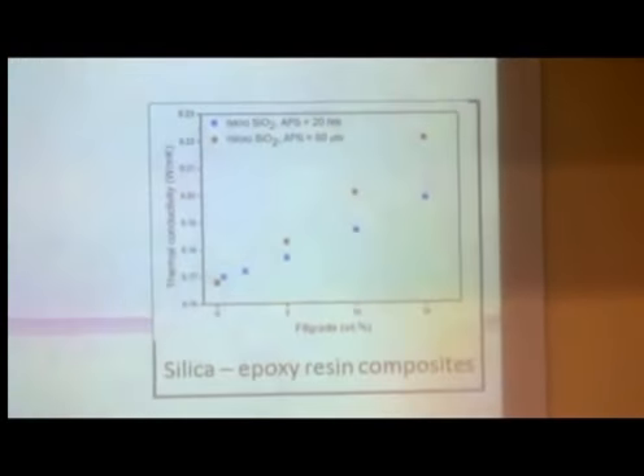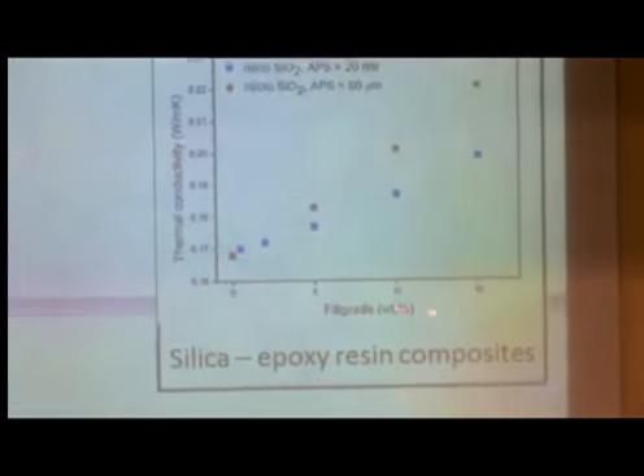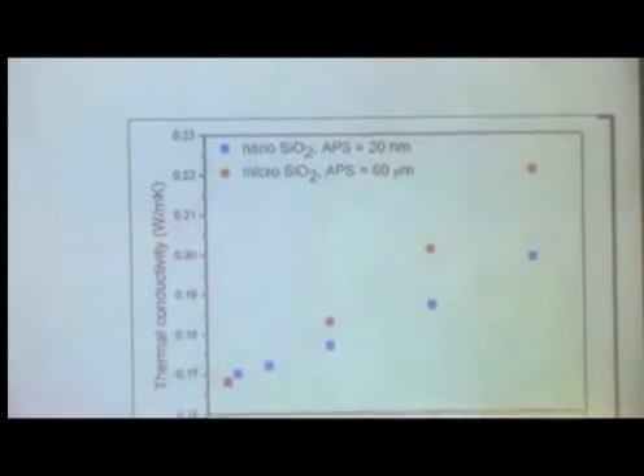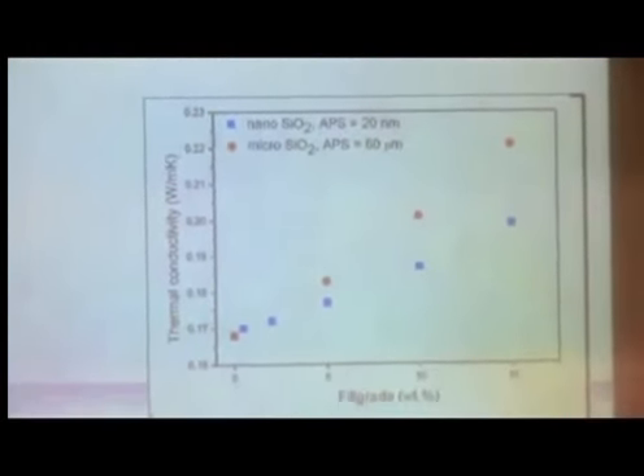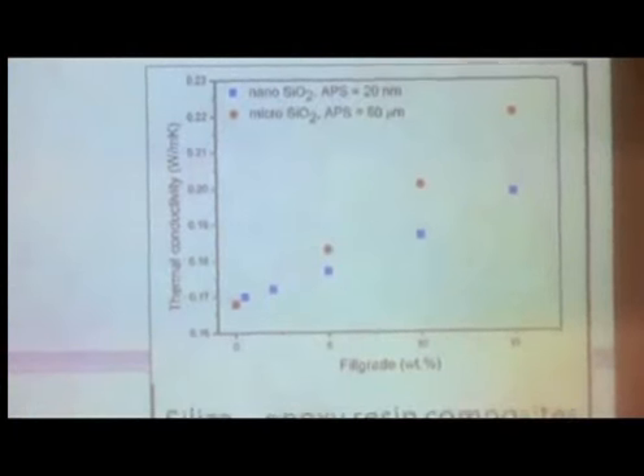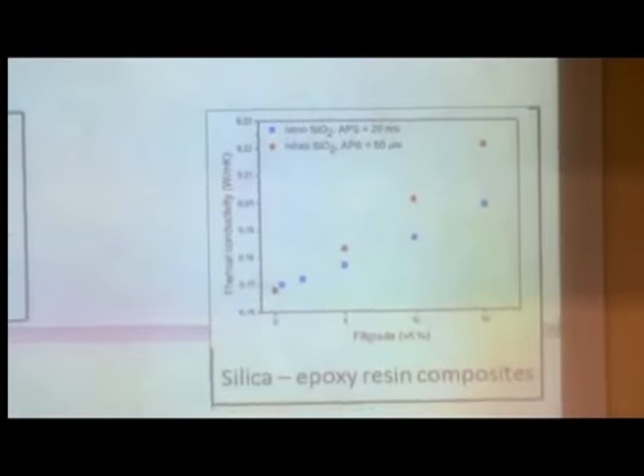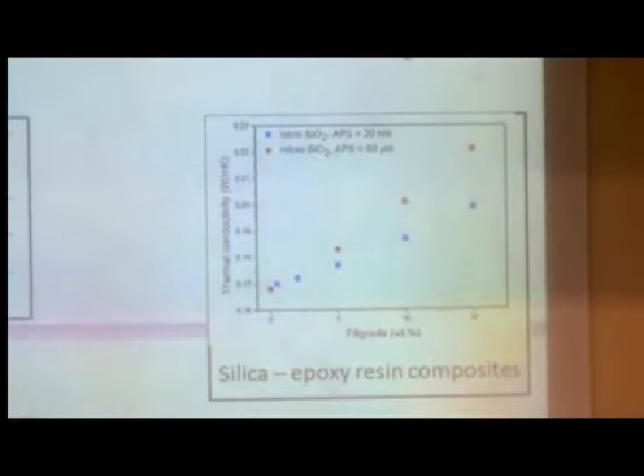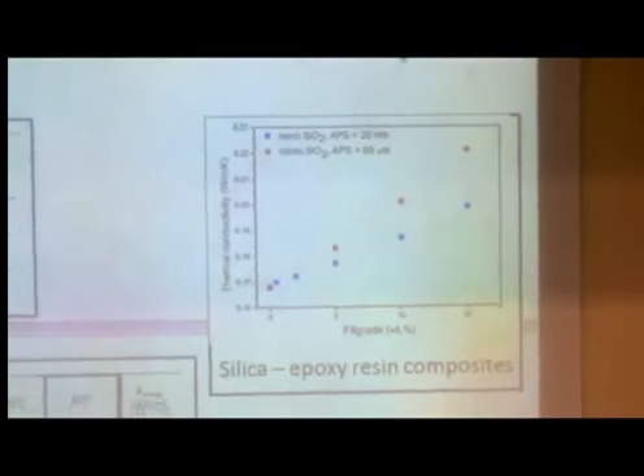Another graph is the graph we would understand, because here we see a silica epoxy resin composite, fill grade versus thermal conductivity. Blue is nano silica, red is micro silica. We see that the micro composite wins. That's what we would expect. More scattering in the nanocomposite, so less conductivity. However,